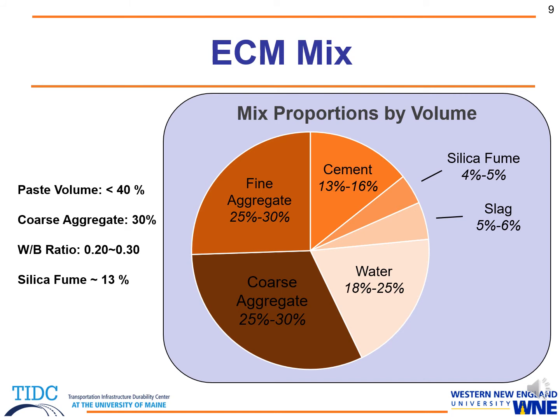Water, right around 18 to 25% by volume was used, and this equated to a water to binder ratio of right around 0.2 to 0.3. And this is pretty typical for any UHPC. Coarse aggregate also, towards the end of our mixes, increased upwards of 30%, and that was an important property for us because that's going to drive the cost down because it's taking up a lot of our volume. And the fine aggregate topped off at right around the same 25 to 30%.